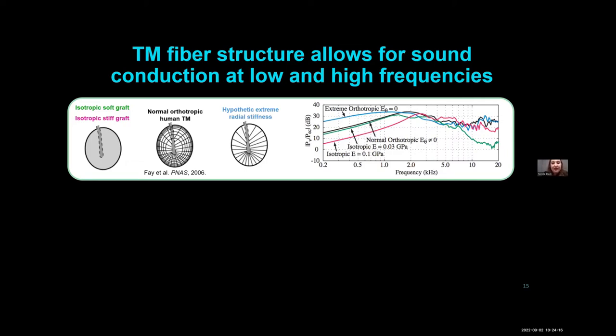And so essentially by comparing this to a TM that's been modeled as a completely soft material, in green here, you can see it's been modeled as an isotropic tissue with about a 30 megapascal stiffness. You can see at low frequencies, it can vibrate very well, but at high frequencies, it drops off a lot. It can't actually move the ossicles all that well. Whereas the converse is true if you have just a purely stiff eardrum, so something like cartilage with a stiffness closer to 100 megapascals. At high frequencies, you can see it vibrates pretty similar to the normal eardrum, but at low frequencies, there's a pretty significant decrease in the amount of pressure that can be transferred because essentially it can't match the impedance of the air, this very stiff tissue.